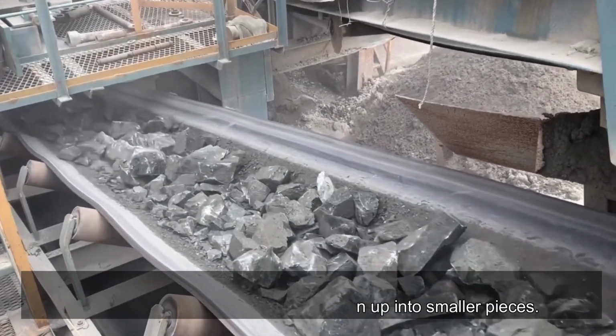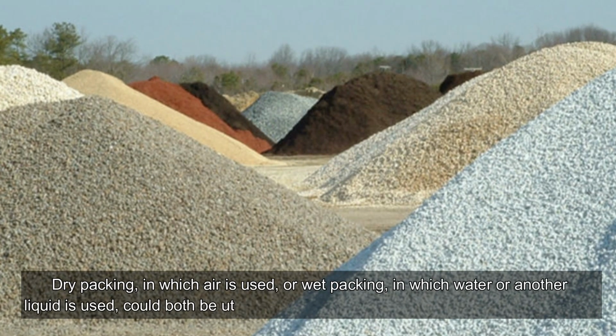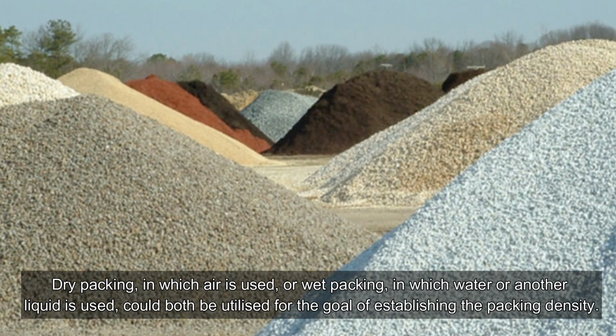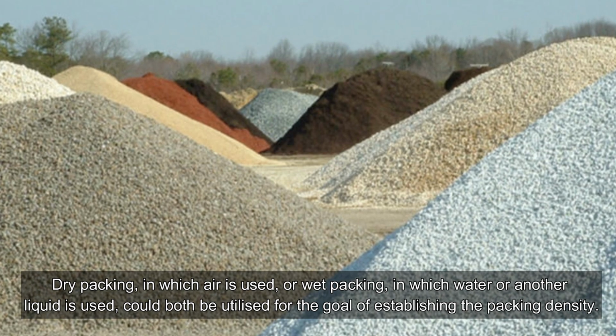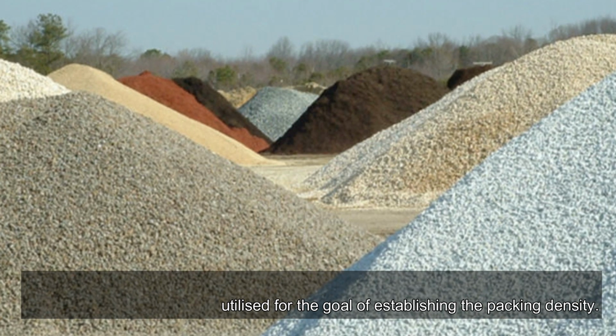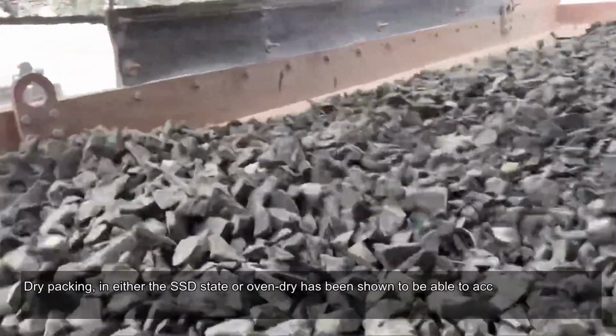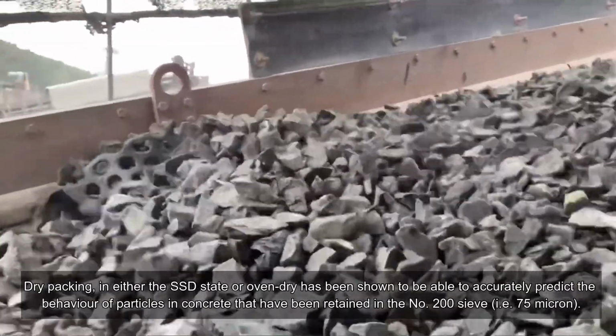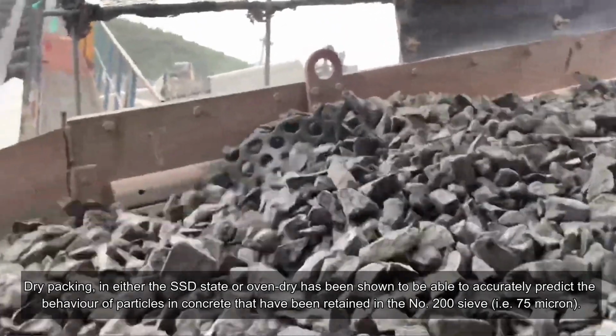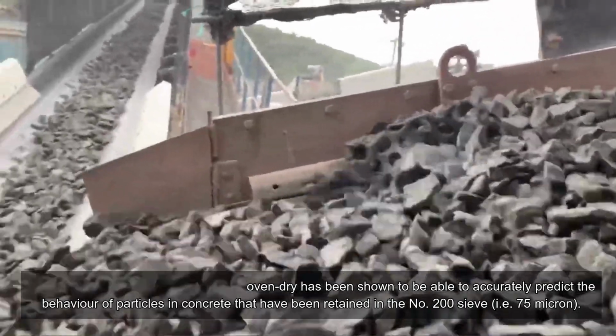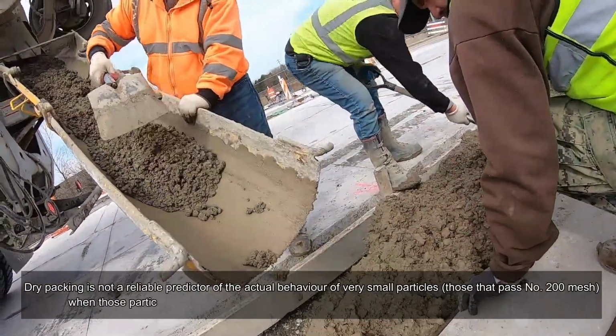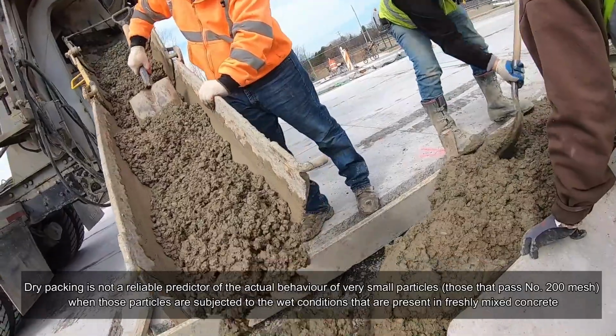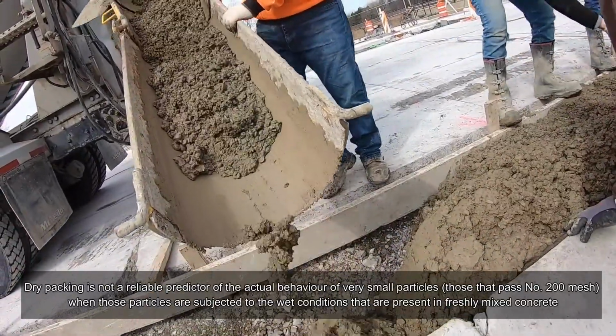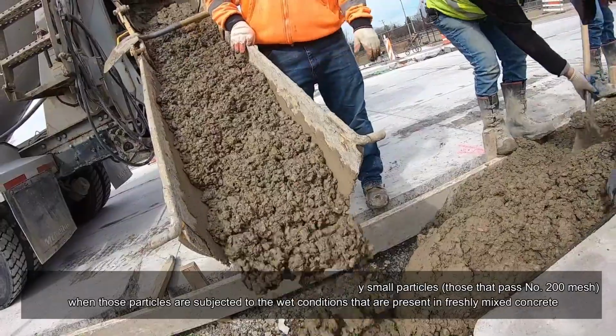into smaller pieces. Dry packing, in which air is used, or wet packing, in which water or another liquid is used, could both be utilized for the goal of establishing the packing density. Dry packing, in either the SSD state or oven dry, has been shown to be able to accurately predict the behavior of particles in concrete that have been retained in the number 200 sieve, i.e. 75 micron. Dry packing is not a reliable predictor of the actual behavior of very small particles, those that pass number 200 mesh, when those particles are subjected to the wet conditions that are present in freshly mixed concrete.